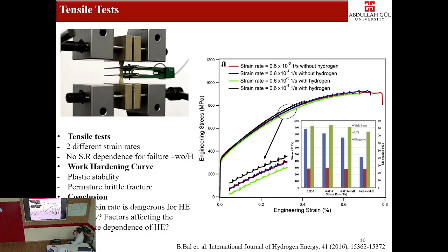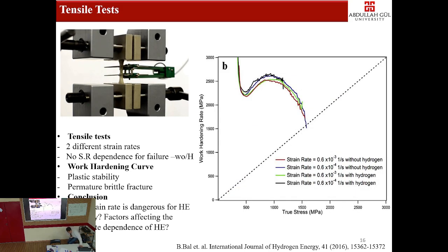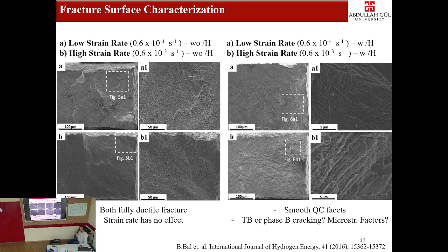We ran tensile tests with different strain rates and observed much more embrittlement at lower strain rates. For the higher strain rates, green and red, maybe 10% ductility loss, but here we have 45% ductility loss. And we tried to use the work hardening rate to see whether we reach plastic stability or not. We did some SEM fracture surface analysis. We see both show ductile fracture, but with hydrogen, the fracture mode changed from ductile to quasi-cleavage.